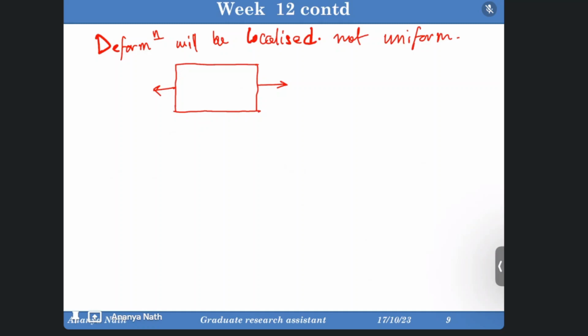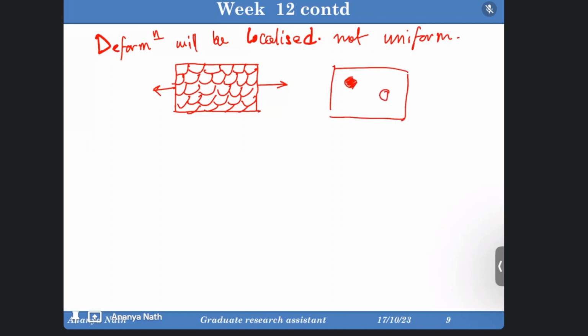No, no. It's because if this is an alloy, then the alloy is made up of the same grains. So there can be misorientation in the grain, but the grains are made of the same particles. So whenever there is deformation, according to the grain size, the dislocations present over the grains will get elongated. But the elongation will be uniform to the lattice. But here in case of metal matrix composite, there are some grains, there are some particles, and there is some interface. So there are three types of things. In the interface, the grains will act differently. The grains where no particles are present will act differently, and the particles themselves will act differently.